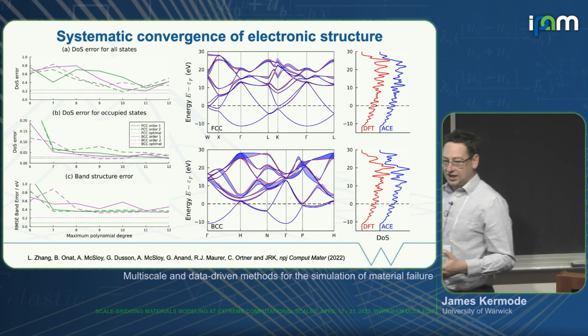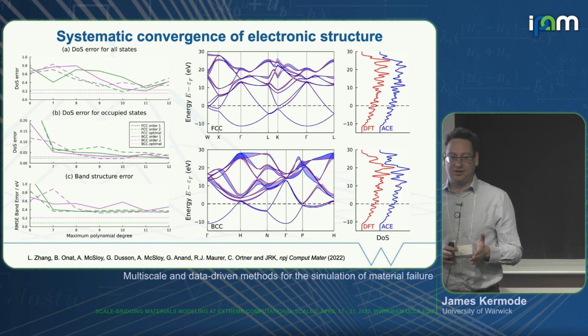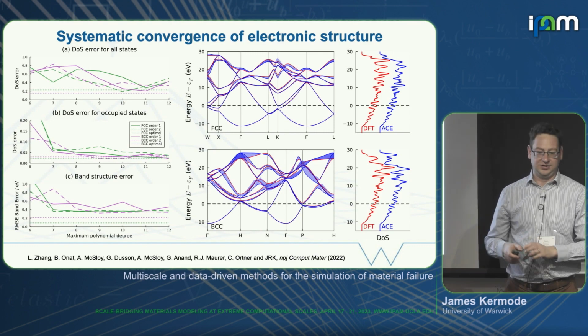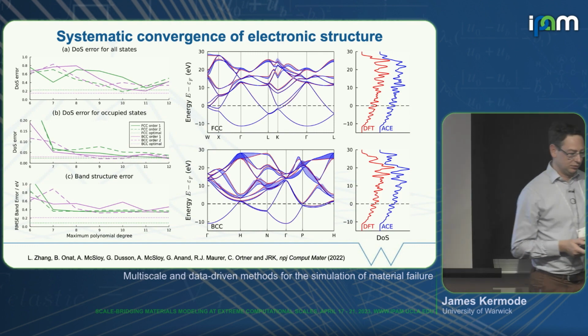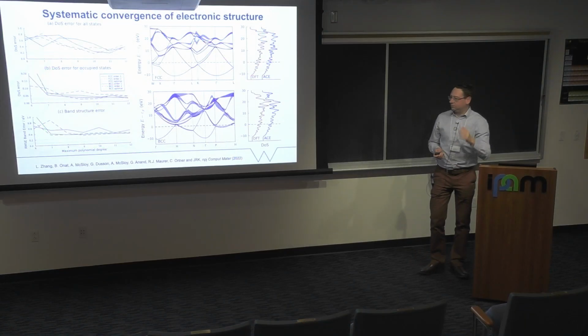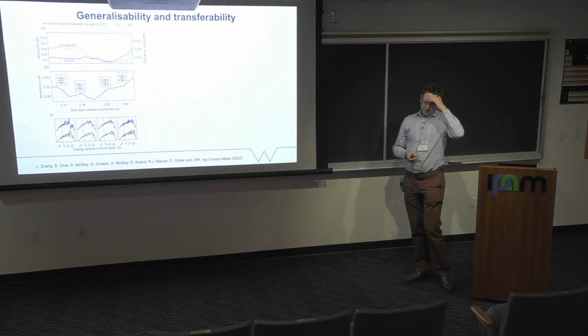So if we make some choices about where to cut off the size of the basis separately for each of the different blocks in the matrix, we can come up with an overall model that doesn't overfit and that works well. And these are the predictions that we get from it that are in good agreement with reference DFT calculations. So far, that's not really showing extrapolation, so we want to try something a bit more challenging.